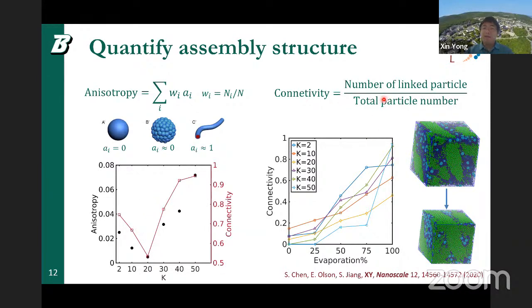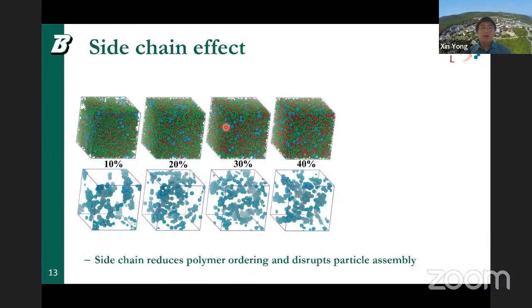And then the connectivity, which is counted by the number of linked particles over the total particles, will also exhibit a similar behavior. But in time, as the evaporation goes, we always see a monotonic increase in connectivity, which makes sense because it basically squeezes the particles together. And so that demonstrates the side chain, for how its rigidity influences the system.